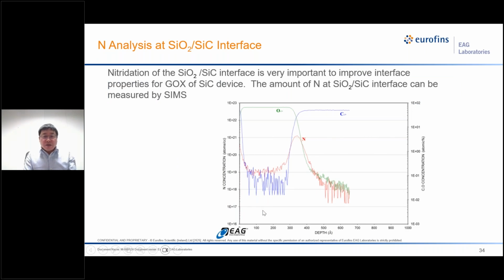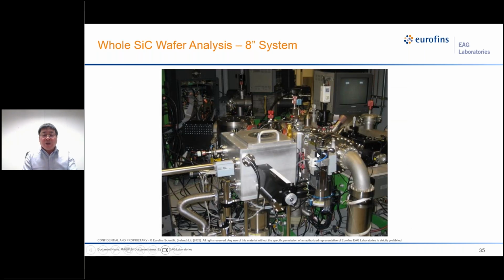It's found the interface of silicon oxide and silicon carbide has a lot of defects. Nitric oxide post-oxidation annealing is a standard industrial method to passivate the defects at the interface. So the nitrogen can be measured with SIMS. Here is the result. We can measure the whole wafer without breakage.